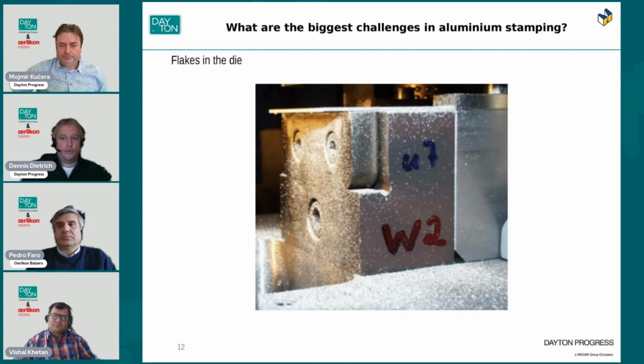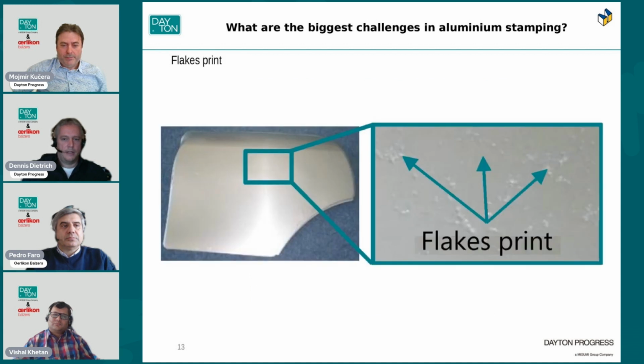And this picture shows flakes in the die. Flakes refers to particles that are detached from the tool during the cutting process or released from the cutting zone and spread uncontrollably within the die and the press. The consequences are marks on the sheet metal parts. Here we see a fender with such markings, which lead to rework or scrap or damage to the tool.